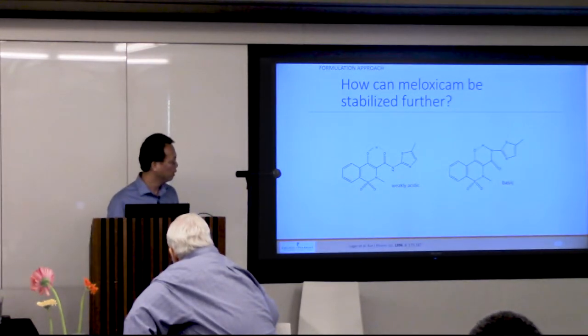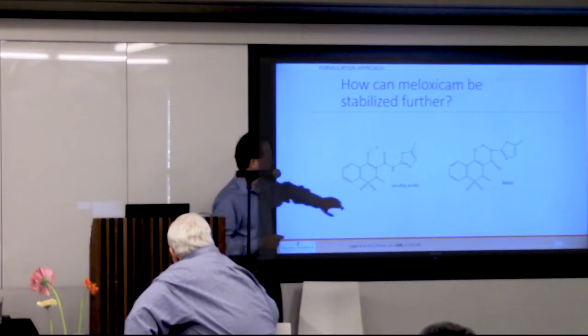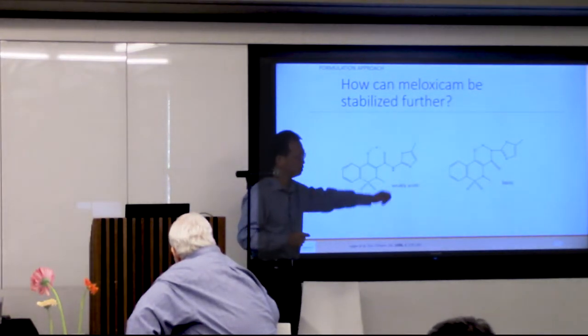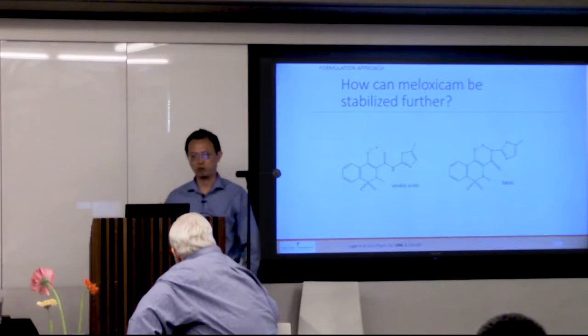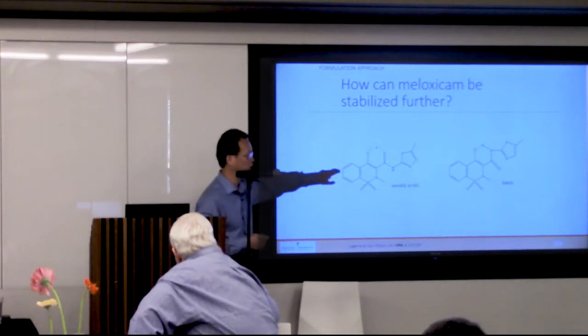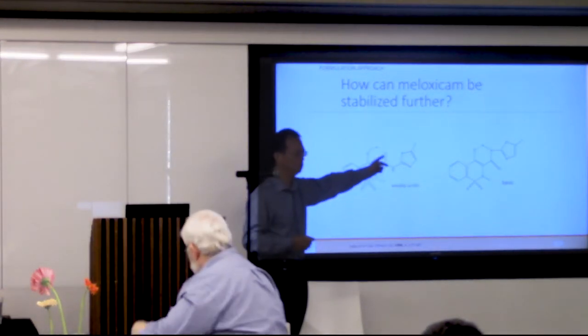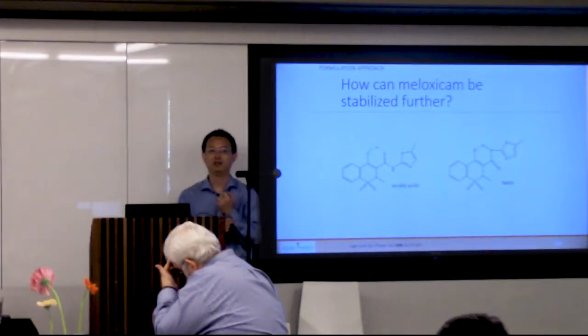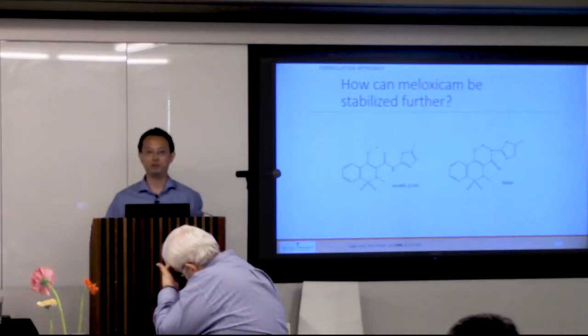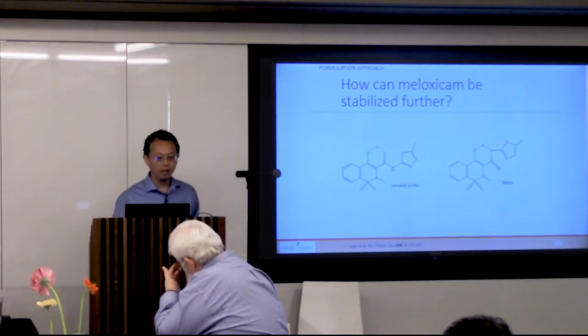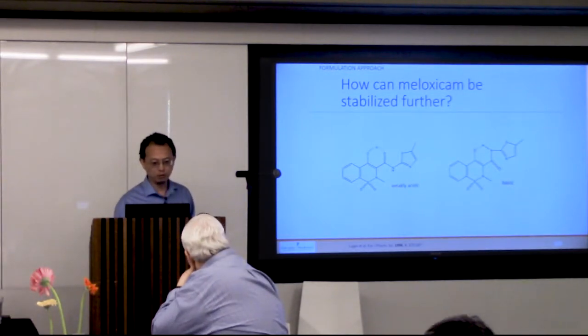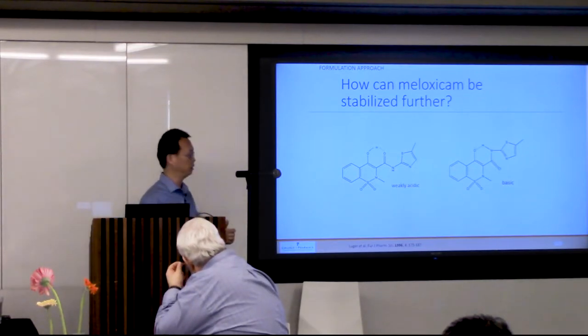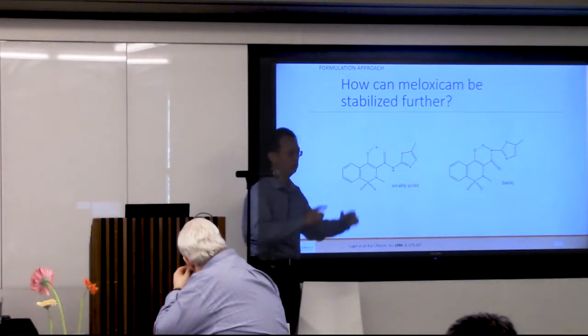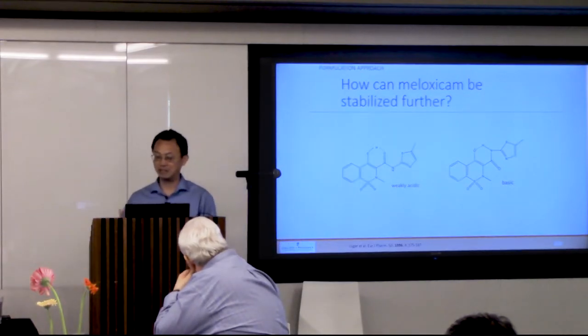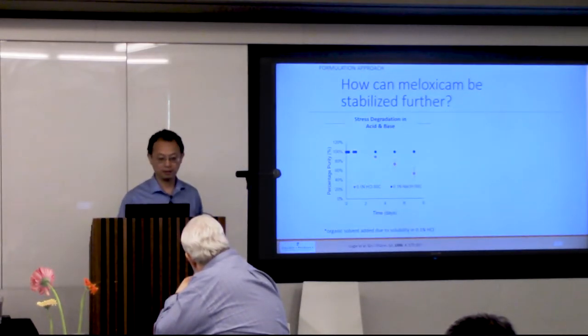Earlier I mentioned how meloxicam degrades. You know, amides typically are very stable because of the resonance structure of the amide, right? It's a single pair of electrons from the nitrogen. But in the case of meloxicam, because of the intramolecular hydrogen, that actually made meloxicam not so stable. Now in the ionized state, meloxicam actually is quite stable because of this intramolecular hydrogen bond, and this amide actually gets locked in that ring structure. That's one of the reasons meloxicam actually is stable at high pH.